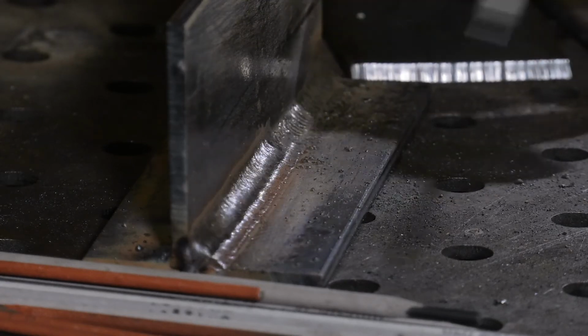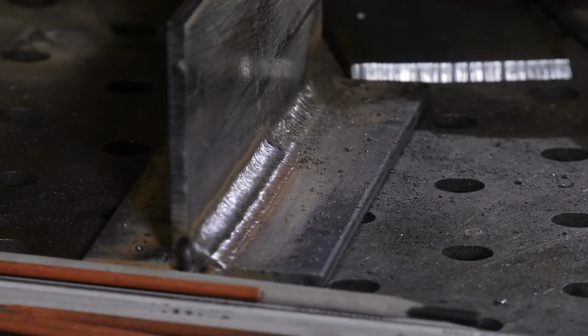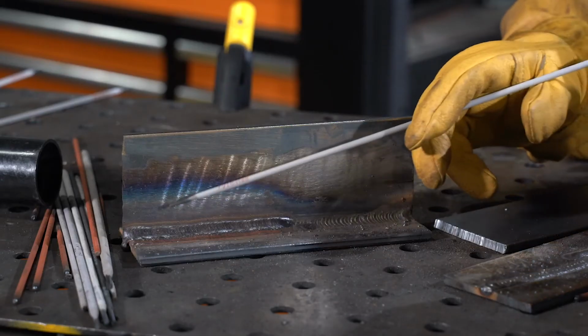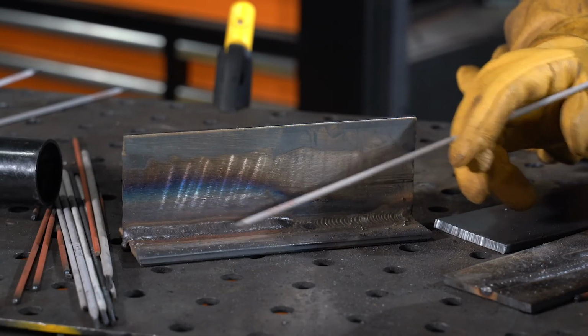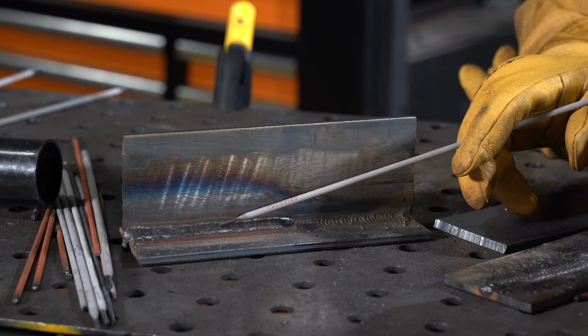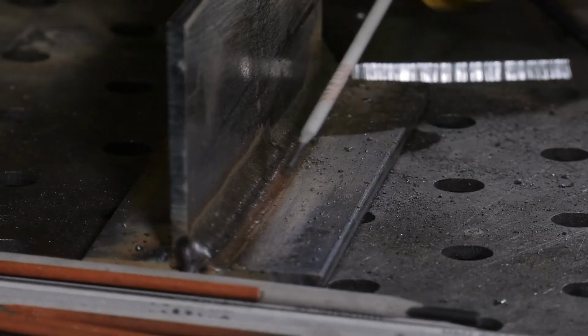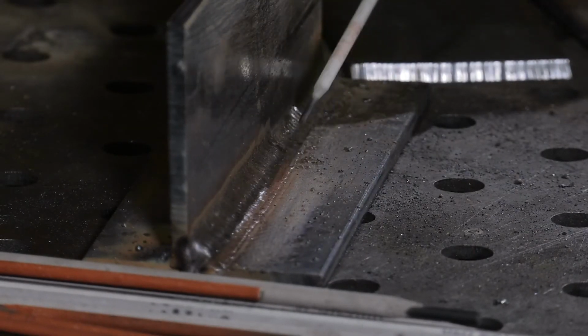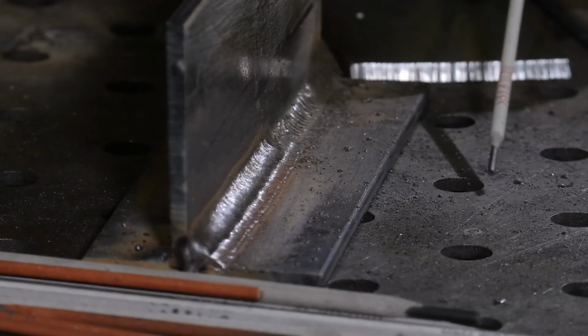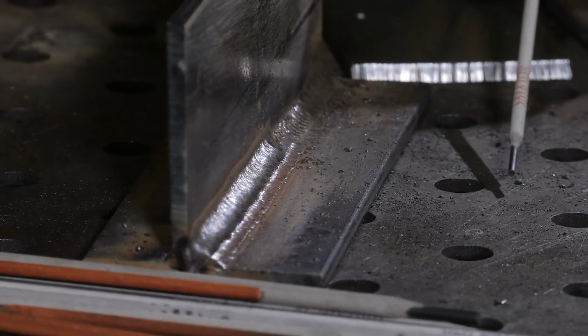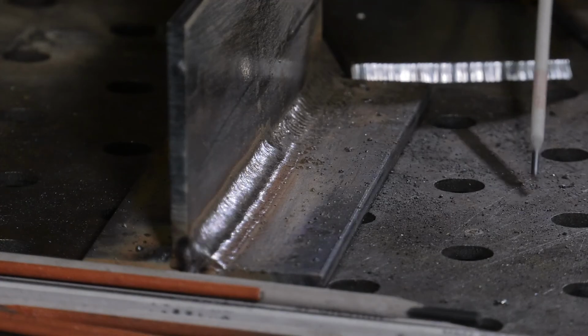You notice the profile of the weld's quite a bit smoother. When we ran that, not much motion at all with the electrode, just kind of a drag and a little bit of maybe side to side to keep a uniform width as we went across. In tandem with these 2, 6010 and 7018 welds here, it's a very common practice that you might see in any AWS welding procedure.